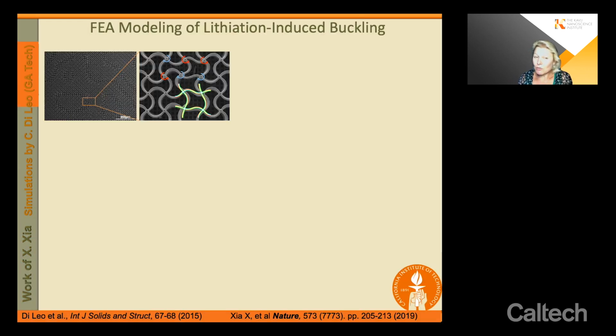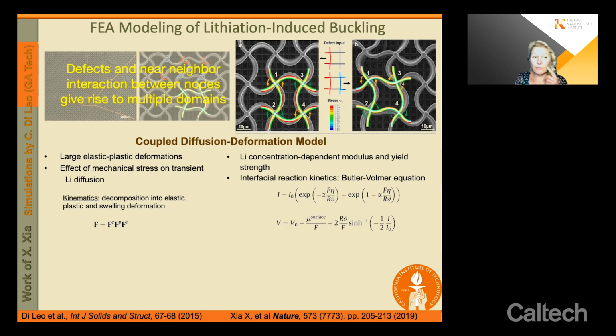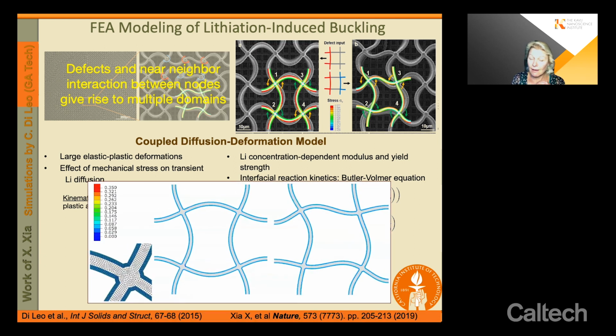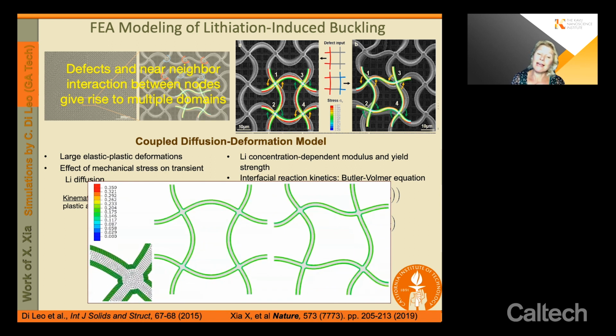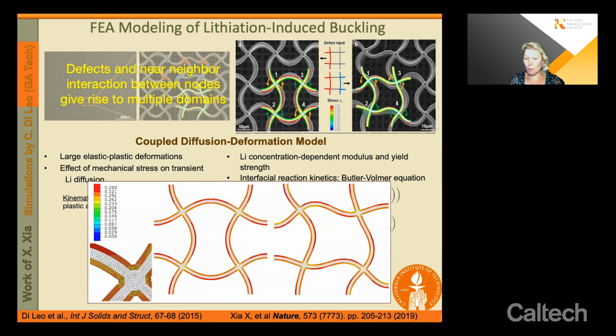So it turns out that when you start lithiating these materials, sometimes your nodes can counter rotate, and that leads to this kind of a bowed out buckling event. But sometimes they can co-rotate, in which case it leads to this very frustrated type of an architecture, which creates a boundary. And so that's what you see here, that some of them look like perfect domains, and some of them look like domain boundaries. So we collaborated with a Professor Claudio Di Leo at Georgia Tech, who helped us explain using a model for why this would be occurring. And so this is what he computed, that as a function of lithium concentration that's dissolving and diffusing into these architectures, it's possible to elicit both of these shapes.